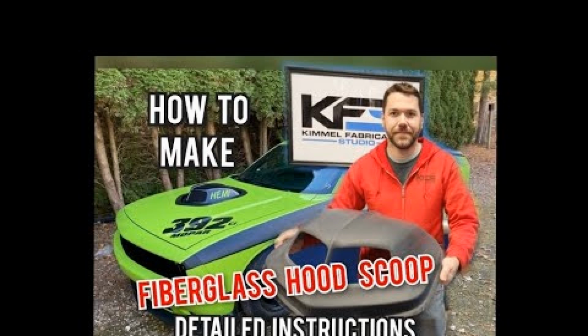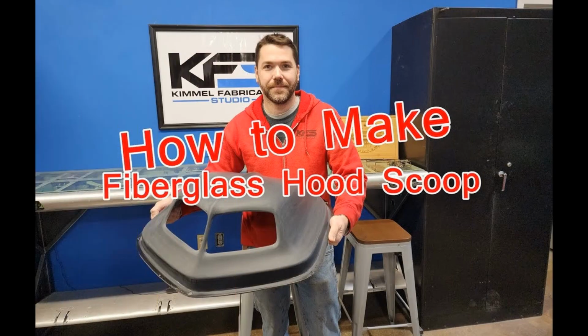To make a fiberglass hood, you need to apply the diluted solution liberally to the surface of the hood. Let it dry a little. Cover the hood with plastic film, and try to expel all air bubbles. Lay sheets of 50 glass fiberglass with an overlap of 2 to 3 centimeters. At the edges of the hood, do not leave more than 2 centimeters of material. Impregnated with resin, it will flex.